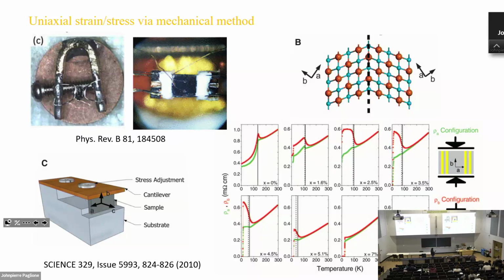This is from about 15 years ago, from where I did my PhD, another group. What they did is really use a mechanical way to apply the strain. You have some metal and a screw. You screw it in or screw it out, and you apply a strain on the sample. With this very simple setup, they can almost fully detwin the sample.